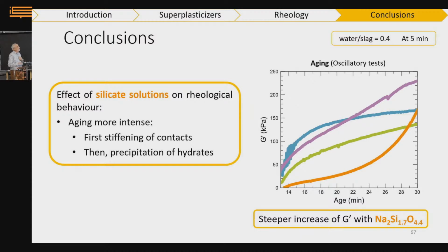So in my opinion, this is the fundamental difference between those behaviors here. As I said, contact stiffening, and then at some point you will have nucleation and so on. But here we have immediately from the start this phase separation that has no barrier, just as in a sol-gel reaction, and proceeds continuously. And this is because I already have silicates in solution. So you see the two studies come together here, and we are dealing with very different phenomena at the molecular scale, but that translates to very different macro scale properties, which is a time evolution of the elastic modulus.